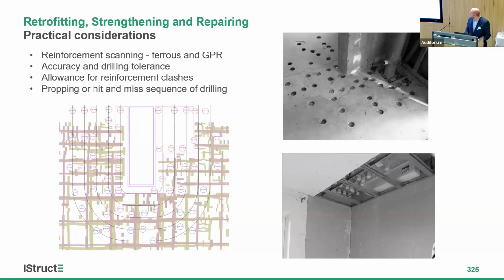Some general considerations regarding installation. A key challenge is avoiding the reinforcement. I recommend scanning the reinforcement with two methods, both using ferrous scanning and ground penetrating radar together. This allows both methods of scanning to be cross-checked against each other to get a better estimate about where the reinforcement is located. You need to consider the accuracy of the scans and the reinforcement congestion and the spacing of the bolts to inform how much tolerance you need.